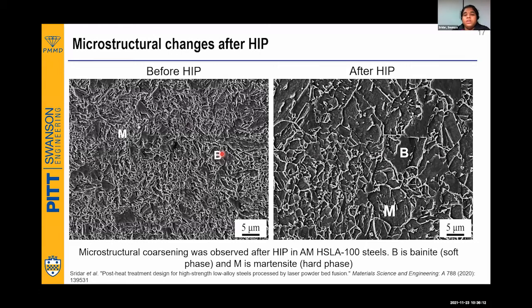Thanks to this very slow cooling rate, my material has become literally spoiled now. If I really check the mechanical properties of this material, though the porosity has been closed, this spoiled microstructure is literally going to reduce the strength of the material pretty badly. So it has.